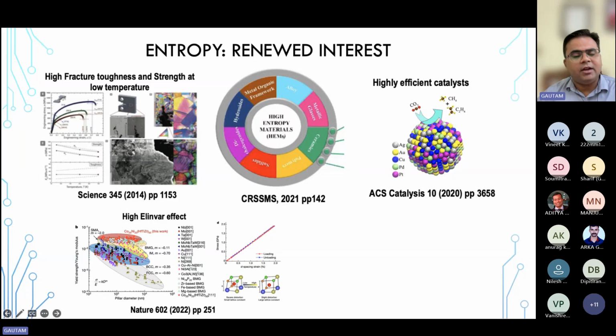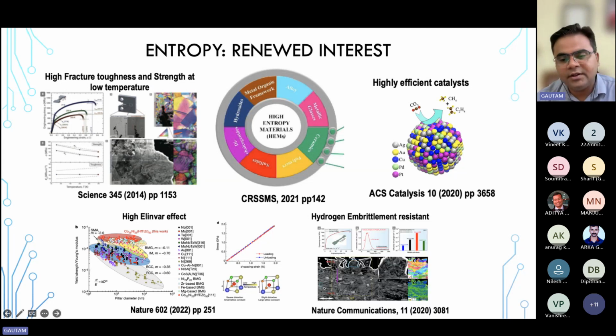This high entropy alloy concept can also be interestingly applicable in designing alloys with a high Elinvar effect, where the elastic constant of these materials can be kept constant as the temperature is varied. Again, the idea was given that at a low temperature, significant distortion is there in this particular class of material. At high temperature, that goes away. So basically, people are engineering the various phenomena associated with high entropy alloys to apply to different interesting classes of material. Another interesting application is high hydrogen embrittlement resistance. This is something where a lot of debate is going on at this moment, whether this class of material shows hydrogen embrittlement resistance property or not.